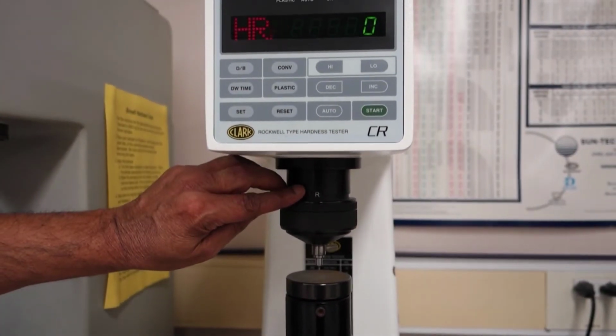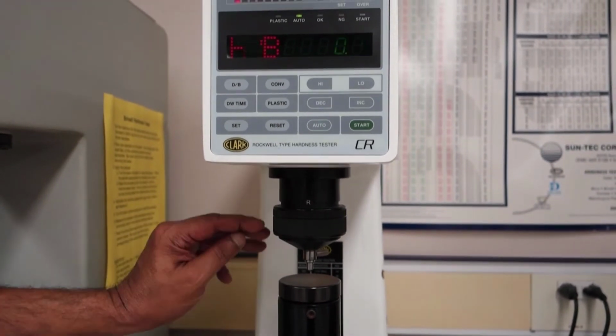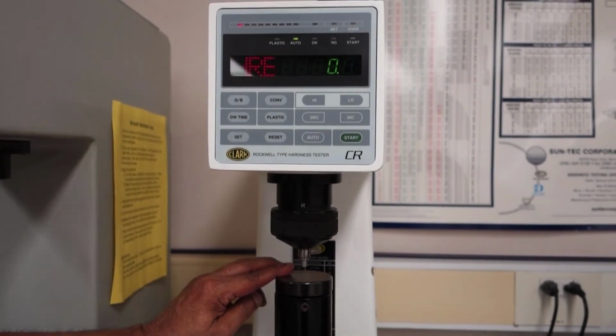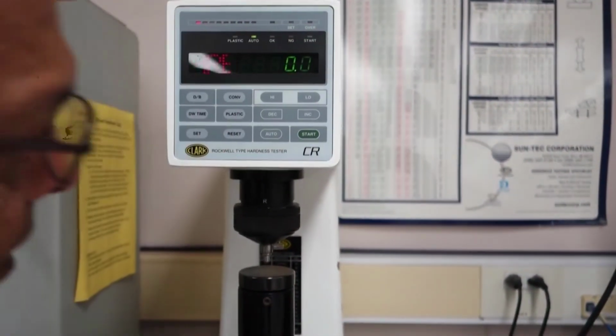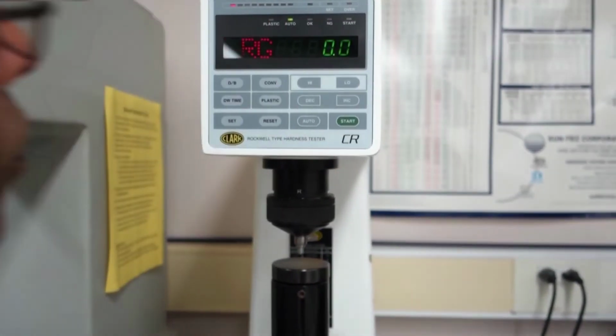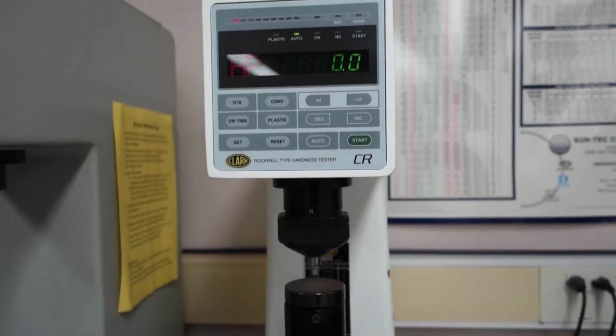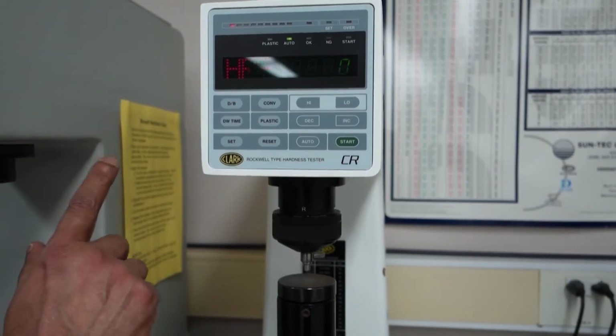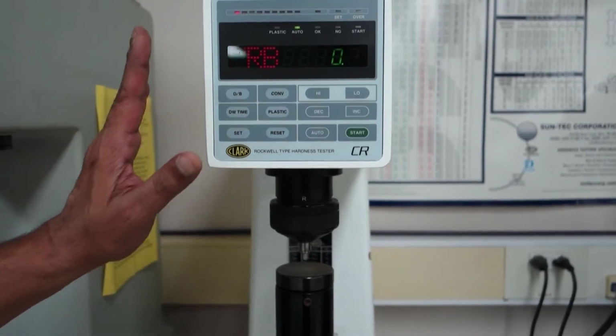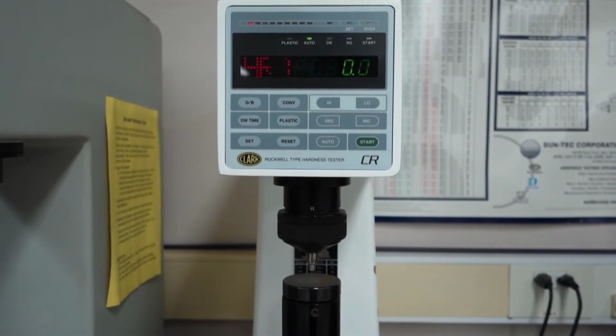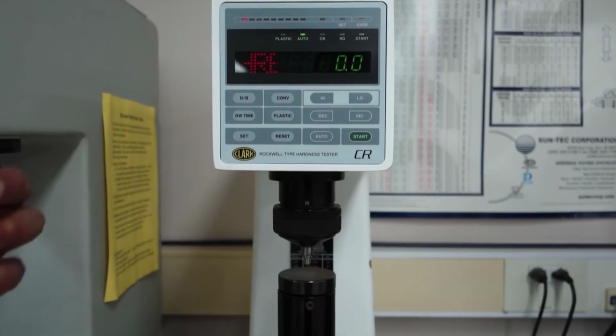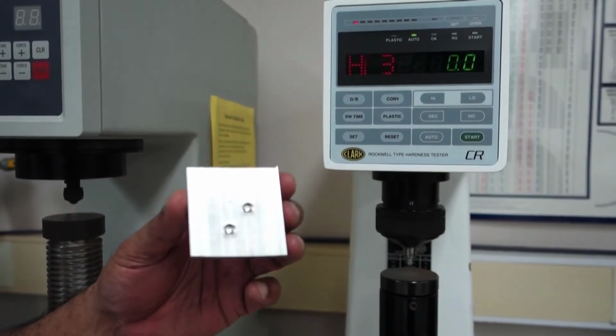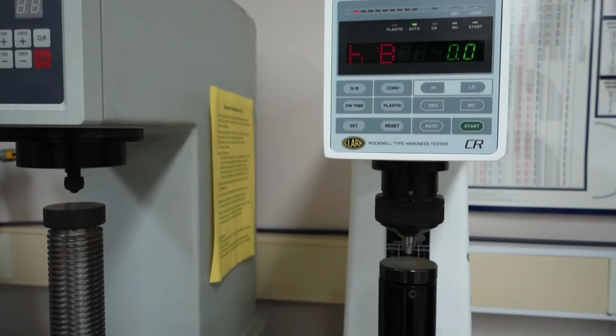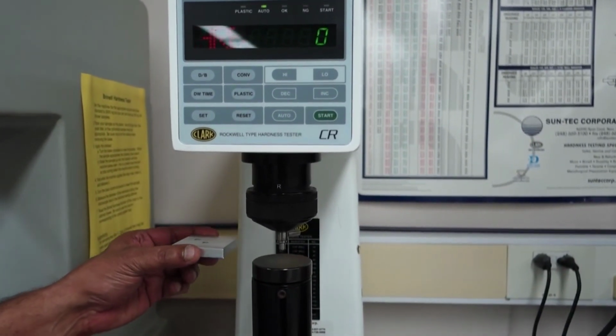So for Rockwell B, we need 10 kg minor load, we need a ball indenter, and we need 100 kg here. If my load setting was not proper or not appropriate, it would select the appropriate scale. So right now 100 kg is the correct scale for HRB. So now we are ready to measure our hardness. So here is the sample we are going to measure our hardness on. So we place the sample underneath the indenter.